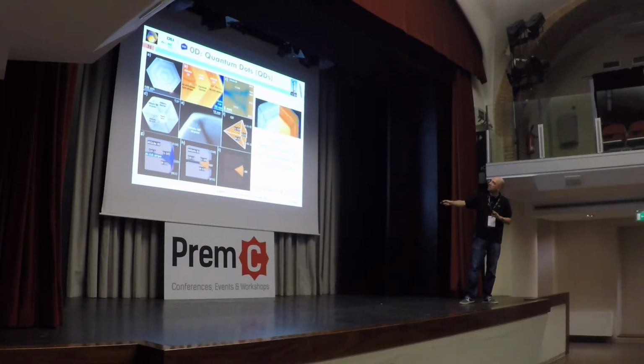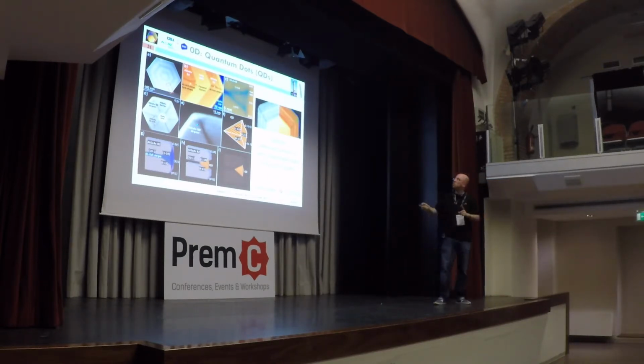So what we have is that exactly in the middle, we have pure gallium arsenide. It's the same that we have here in the nanomembrane. This is a nanomembrane. You can continue like this, and you could see the whole nanomembrane. We were growing aluminium gallium arsenide on top. But due to the different diffusion of aluminium and gallium, the aluminium is mainly incorporated on the edges of these hexagons. It's exactly the same that is going on here. So what we have is a kind of confinement, like a quantum dot confinement.